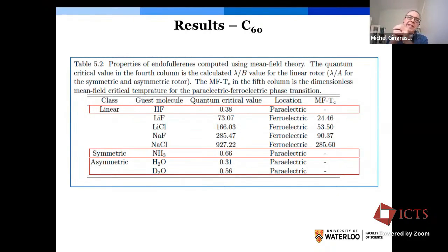For those molecules that have been thus far synthesized, which is hydrogen fluoride, HF, which is a linear rotor, ammonia, NH3, and the asymmetric rotor, such as water, H2O, and heavy water, D2O, what we find is that those molecules should be very deep in the quantum disordered phase. That is, they are so quantum that the energy spacing between the ground state and the first rotational state is very large compared to the dipolar interactions that would describe them. Furthermore, the dipole moment is screened here, reduced by about a factor of 3 compared to the gas phase dipole moment. And so these molecules should not exhibit spontaneous ferroelectric order according to our calculations.